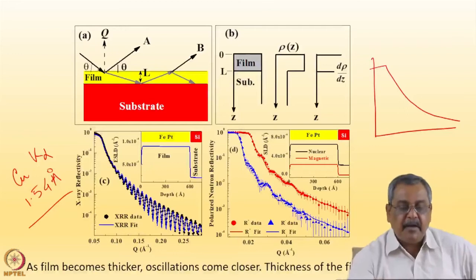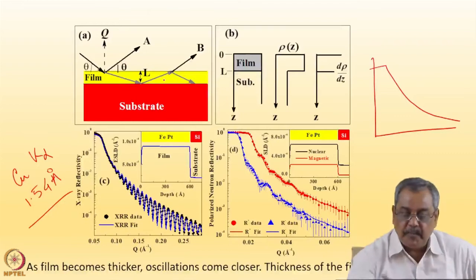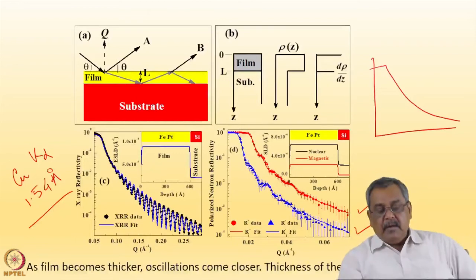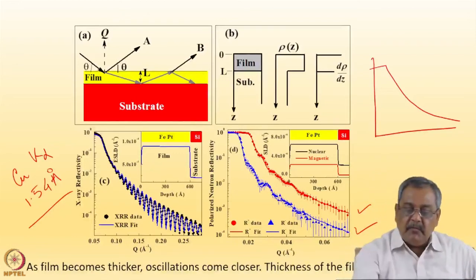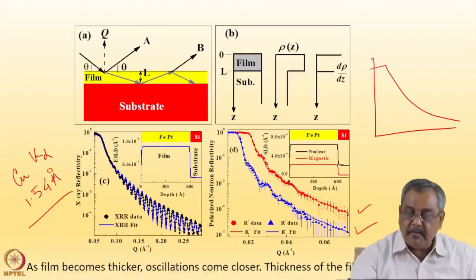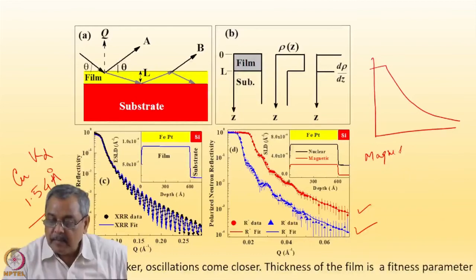But above the critical angle, because your beam is now penetrating the film, you have got these two components, the polarized beam intensities, together with the thickness signature as Kiessig oscillations on the falling edge of the reflectivity pattern. So by fitting this, we get magnetic moment density,